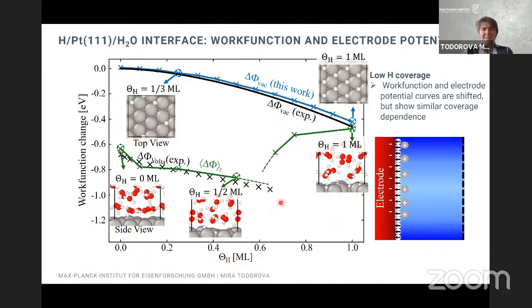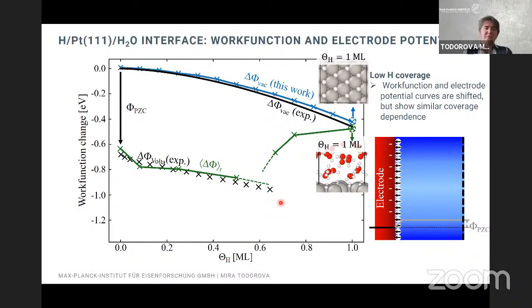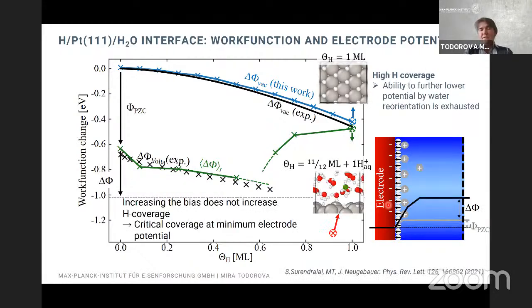Let us try to take this a bit apart. So first of all, if we look at the zero coverage case, this should be just the potential of zero charge. So basically we have the rearrangement of the water close to the interface. As more hydrogen is added, there is a change in the potential, so a potential drop. And so the hydrogen that is adsorbed at the interface seems to be able to screen the charge on the metal electrode, but this works only to a certain region.